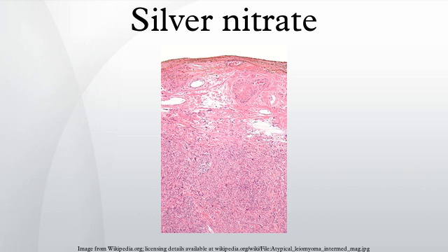Silver nitrate decomposes when heated: 2AgNO3 (l) → 2Ag (s) + O2 (g) + 2NO2 (g). Qualitatively, decomposition is negligible below the melting point, but becomes appreciable around 250 degrees Celsius and totally decomposes at 440 degrees Celsius. Most metal nitrates thermally decompose to the respective oxides, but silver oxide decomposes at a lower temperature than silver nitrate, so the decomposition of silver nitrate yields elemental silver instead.